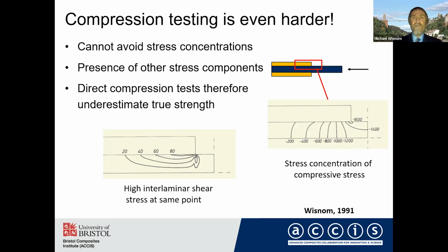So that's tension, but what about compression? Well, actually, compression is even harder. With normal direct compression tests, you can't really avoid stress concentrations or the effect of other stress components. Some FE analysis I did many years ago, we showed how the stresses were higher near the tab, and how we had these very high shear stresses, which are known to be detrimental in compression. So it's not surprising that we get premature failure.